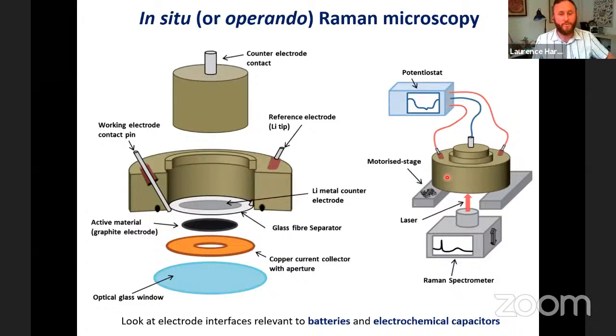So just to finish off the talk, I just want to talk briefly about in situ Raman microscopy. We traditionally use this type of cell setup where we look at the electrode from the backside. So we usually have a current collector with a small aperture, and then we're able to shine the laser through and look at our active materials. So in this case, a graphite electrode.